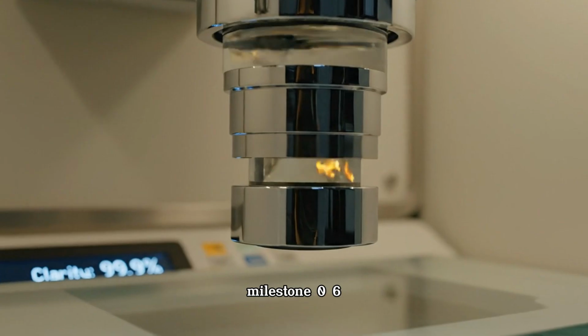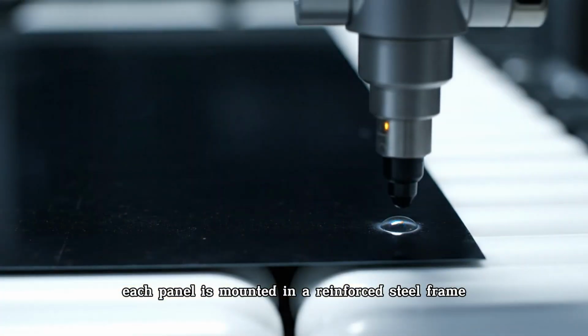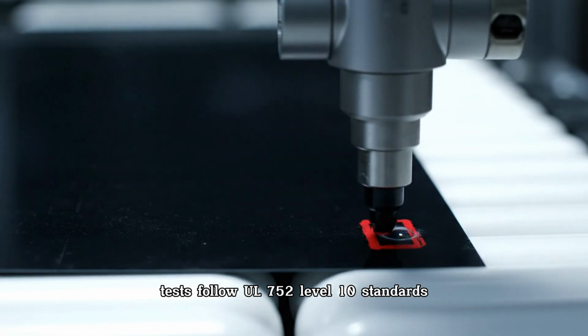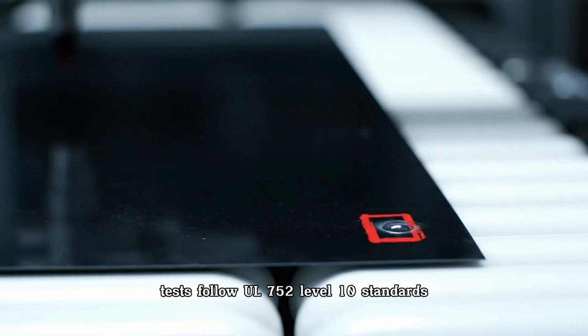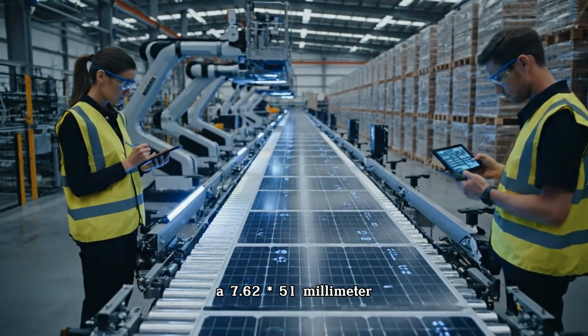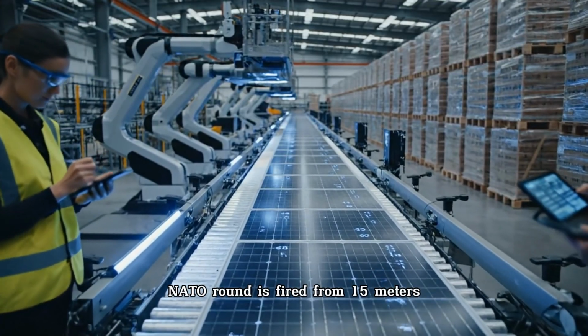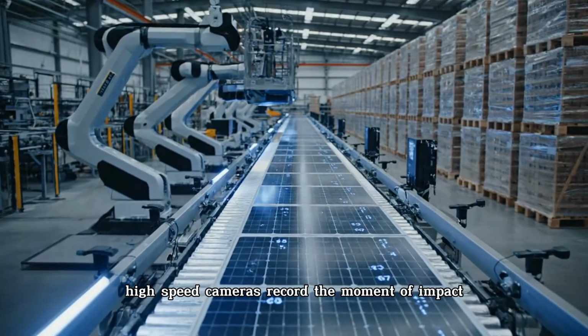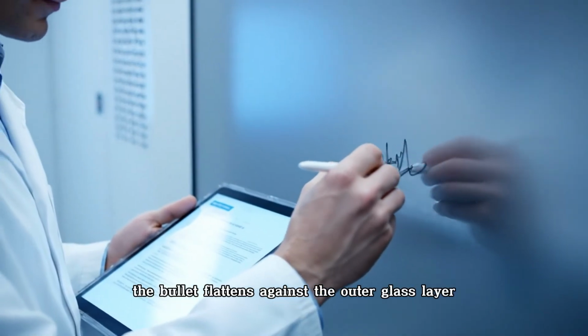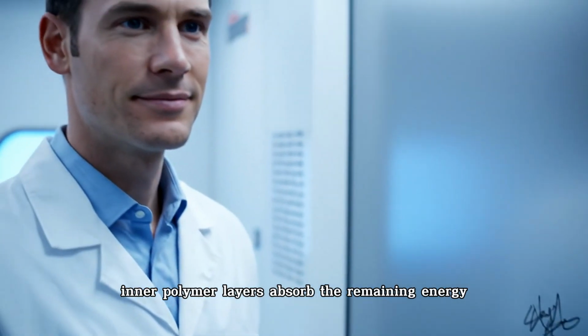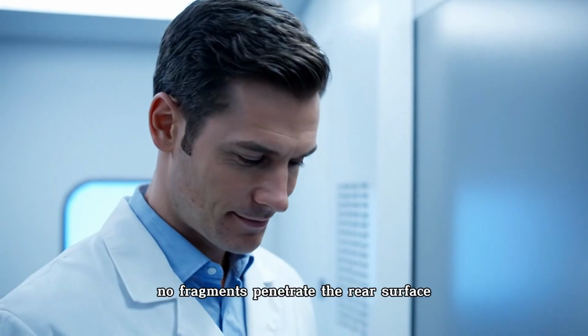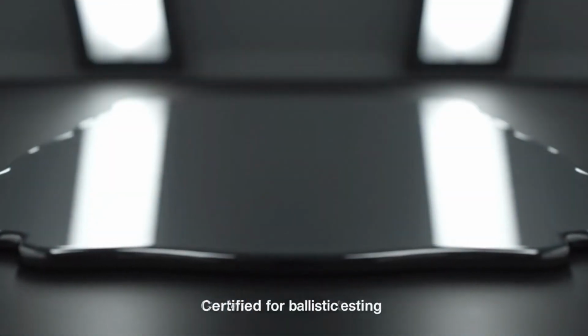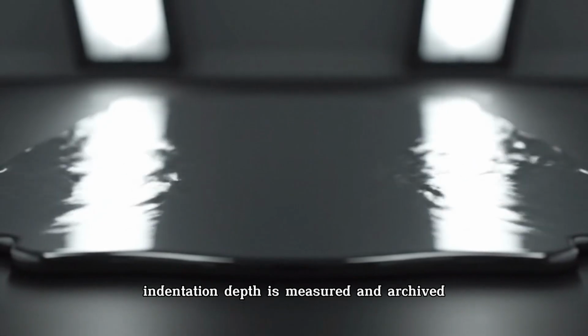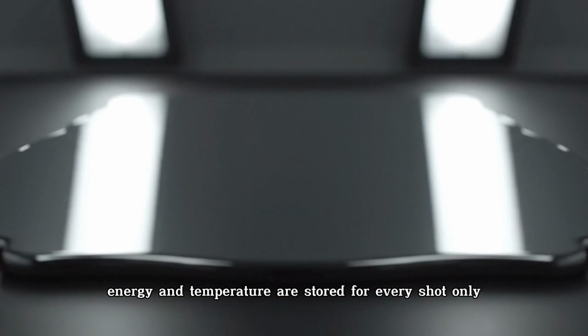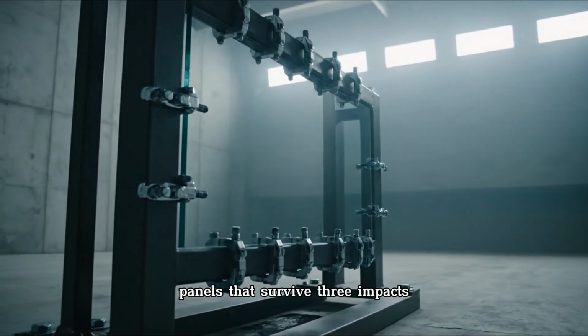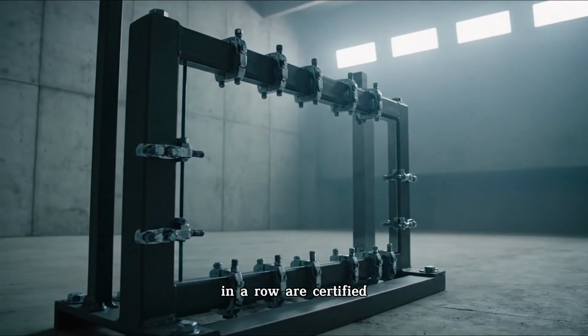Milestone 06. Each panel is mounted in a reinforced steel frame. Tests follow UL 752 Level 10 standards. A 7.62 times 51 mm NATO round is fired from 15 meters. High-speed cameras record the moment of impact. The bullet flattens against the outer glass layer. Inner polymer layers absorb the remaining energy. No fragments penetrate the rear surface. Indentation depth is measured and archived. Impact velocity, energy, and temperature are stored for every shot. Only panels that survive 3 impacts in a row are certified.